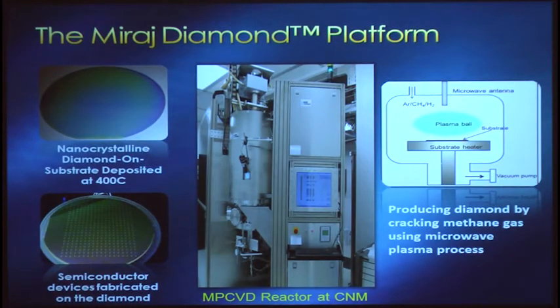Why was it such a breakthrough? Well, we dubbed it the Miraj Diamond Platform for several reasons. One, diamond is naturally an insulator, so it's almost a mirage that it's conducting at this point. But in combining these two things, we have a new platform that enables a diamond-based semiconductor industry, where rather than having a large two-story reactor, at CNM they have a Lambda plasma-based system, which fits easily, as you can see, in one room. It's fully automated, and it enables diamond-based electronics, where instead of using very high pressure and very high temperatures, we're able to use low temperatures and crack methane via this microwave plasma process. So we can take this CMOS-compatible diamond and make semiconductor-based devices out of it.